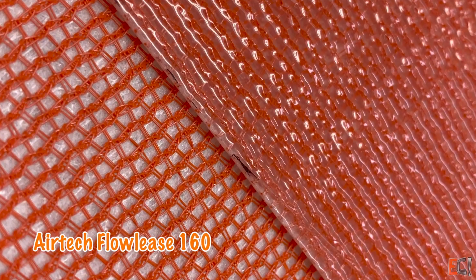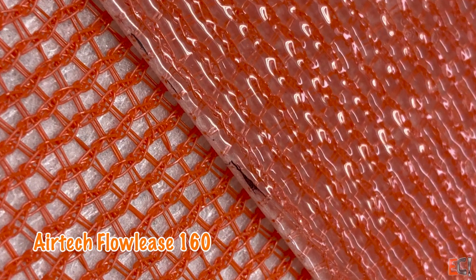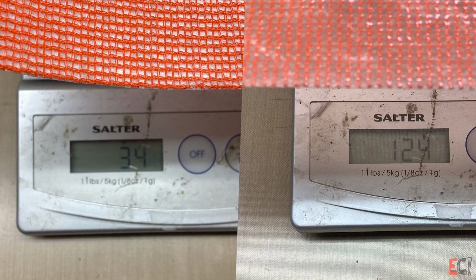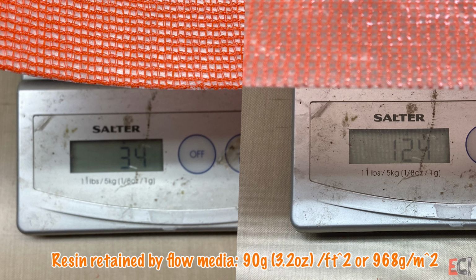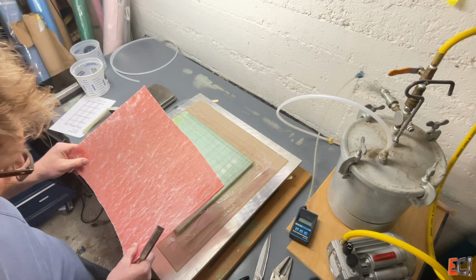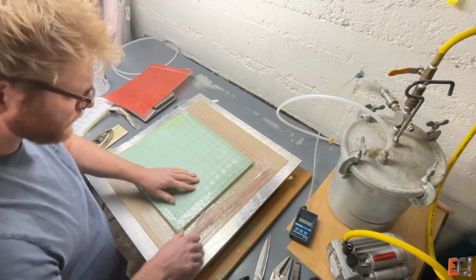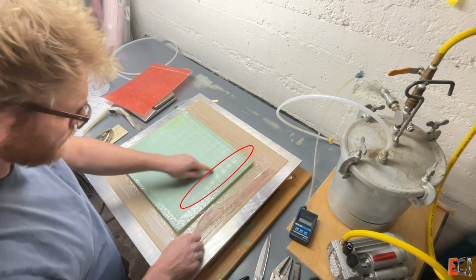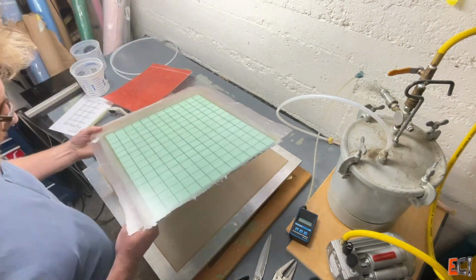And peel off this surface flow. You can see a lot of resin taken by this. When we weigh it out, it comes to about 90 grams per square foot, which is not unreasonable given similar products. And here you can see the little spots where the air was trapped in the top skin, but the bottom looks nice and fully wet out. But you can see just how much resin there is in filling each of those core gaps.